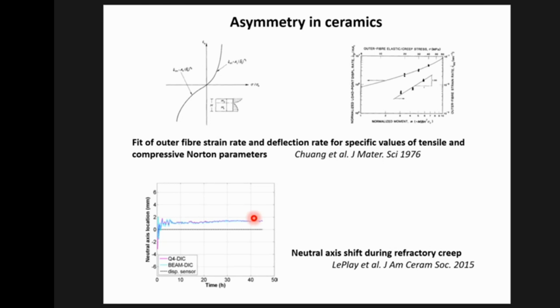The problem with most of these analyses is that they assume that steady state is reached, whereas almost certainly because of the asymmetry, the tension side cavitates, and when it cavitates, it goes on creeping faster. When it creeps faster, it sheds more load to the compressive side. So it's a very dynamically evolving situation.